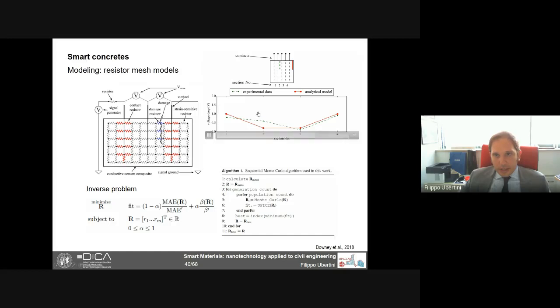If you look at it again from the beginning, you will see that when we add a damage, we have a deviation. Let's see it again. Now we have a good agreement between experiment and model. Then we add the damage in green, deviation. Then we add the damage in red in the model. We move it. Now it's getting to the exact location. Okay, here is the exact location. And then it moves again.